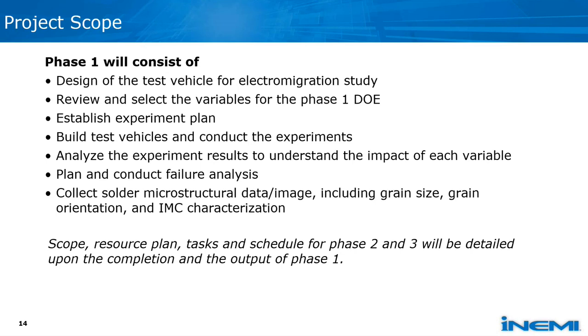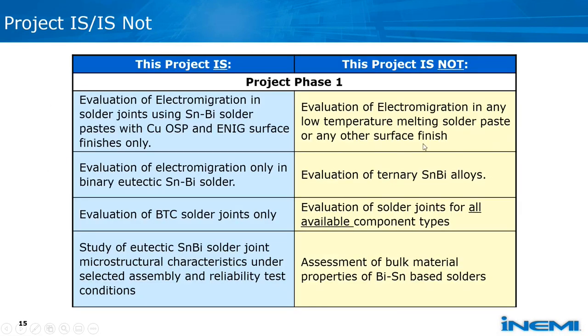Failure analysis of pre and post electromigrated joints will be conducted by collecting solder microstructural images and documenting key data in those images, such as grain size, grain orientation, IMC characteristics, and even presence of voids, as PJ showed in his first couple of slides. The scope, the resources, tasks, and schedules for these two phases, phase 2 and 3, will be drafted after phase 1 is completed and a report is published. Phase 2 and phase 3 contents are still open.